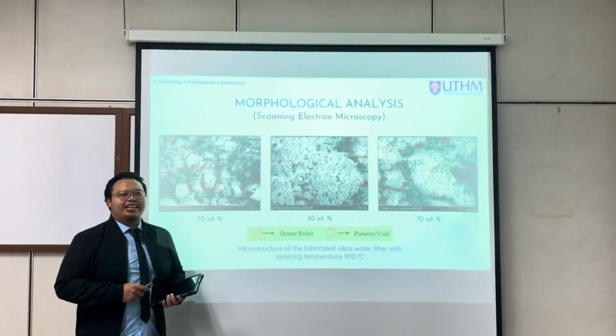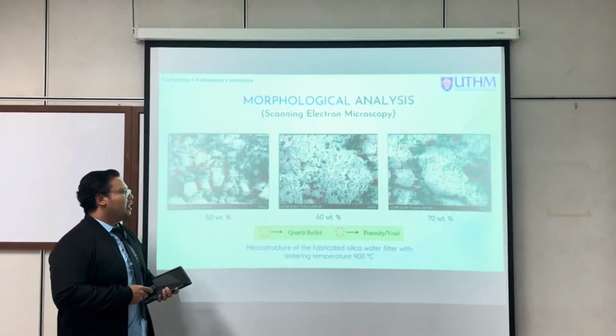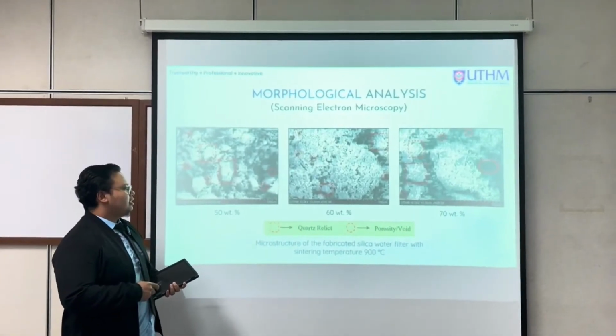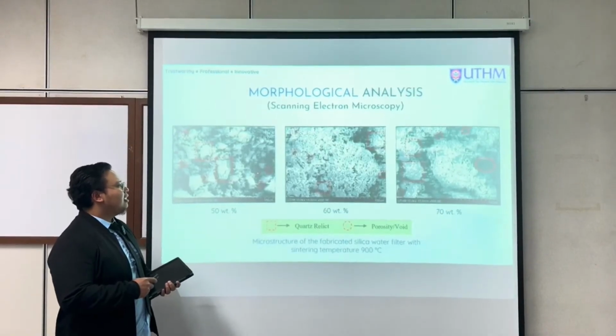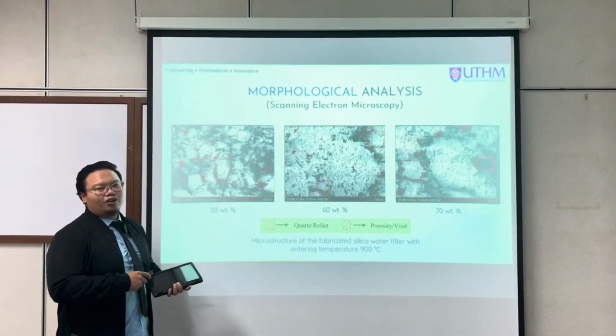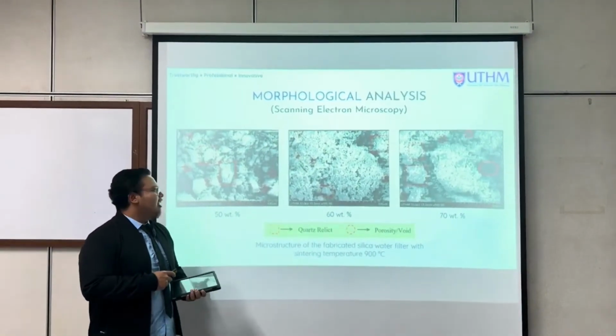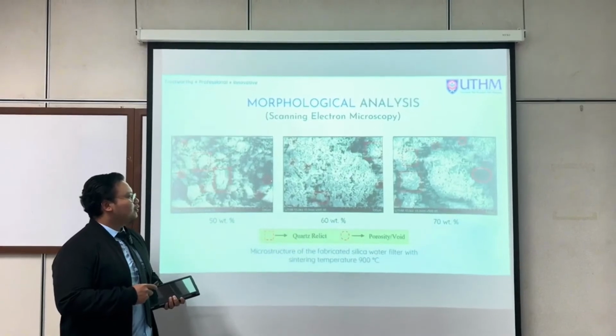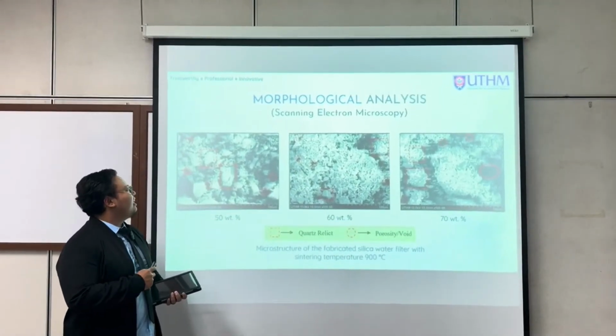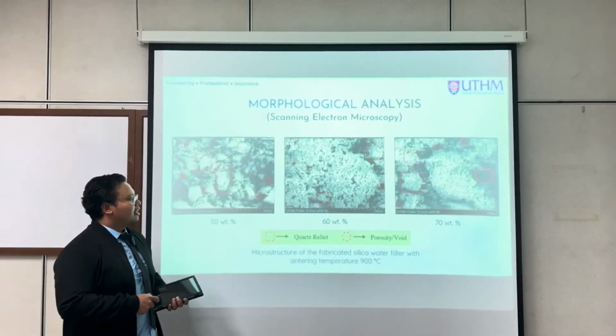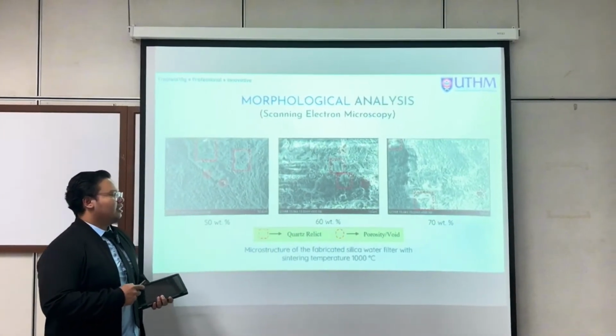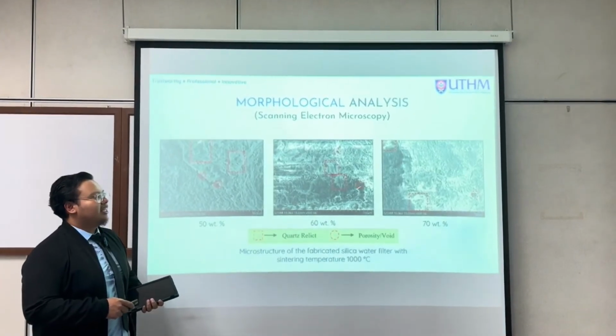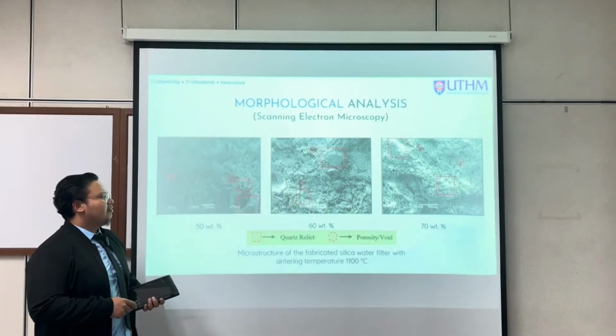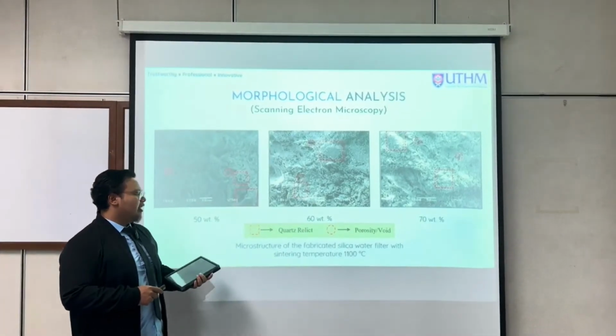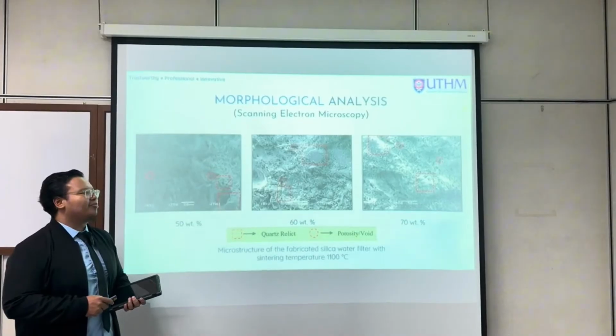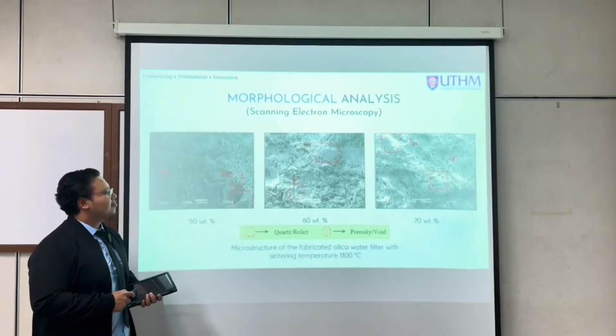For morphological analysis, which is SEM, scanning electron microscopy, we can see that all samples contain silica, and that a lower weight percent of silica produces larger pore size and more pores. This is the SEM for the 900 degrees Celsius samples, and these are the figures for the fabricated silica water filter at the sintering temperature of 1100 degrees Celsius.